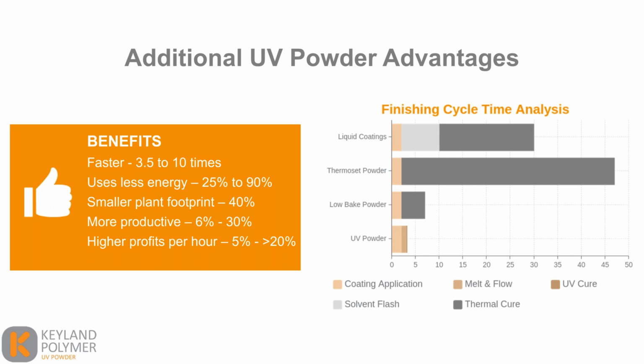So for additional advantages of UV curable powder coatings, comparing it to other coatings, liquid coatings, thermoset powder coatings, and then ultra low bake powder coatings, the benefits are that the systems can be significantly faster. They utilize up to 90% less energy. The systems are significantly smaller in plant footprint. They're much more productive, which ultimately yields higher profits per hour.